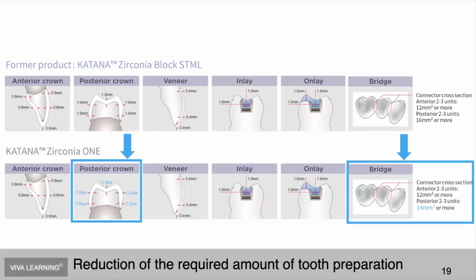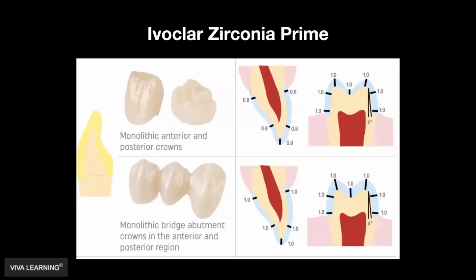And then the thickness of these bridges, the connector between the abutments and the pontics, we can actually streamline and get a little bit thinner now. We don't have to bulk it up for the posterior. We can get it down to 14 millimeters squared for the strength to make sure that the bridge doesn't fracture at this connector space. Now, this is the brand new one on the market.